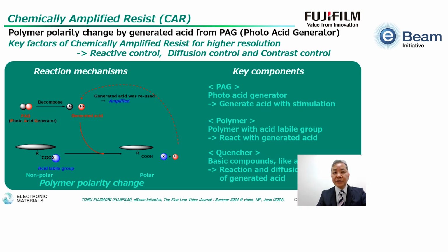Reaction mechanisms are shown here. PAG decomposed by irradiation, generated acid. Acid attacks the acid labile group of polymer to decompose the group. Then, polymer polarity change from nonpolar to polar.